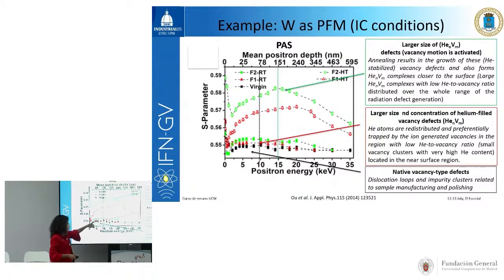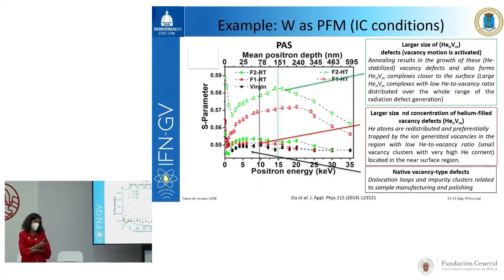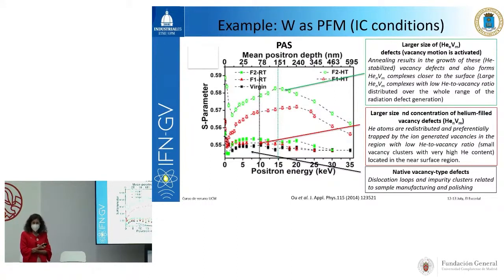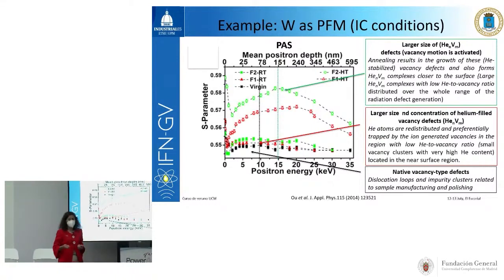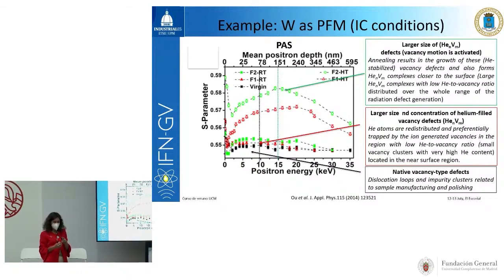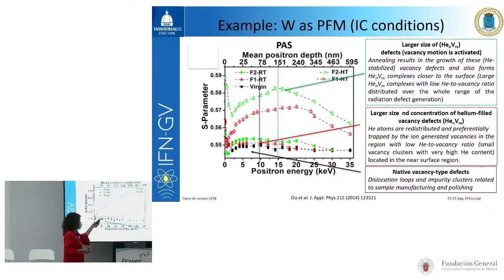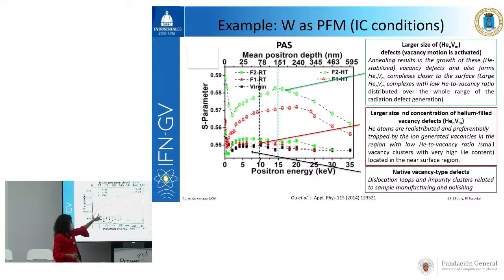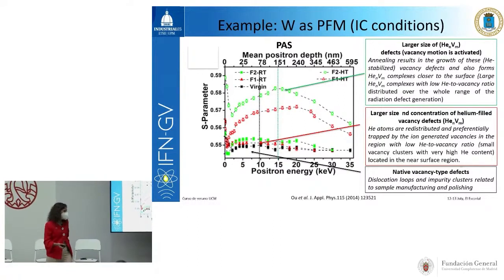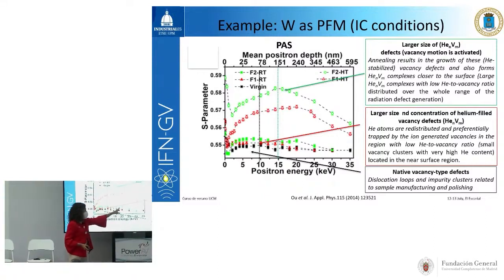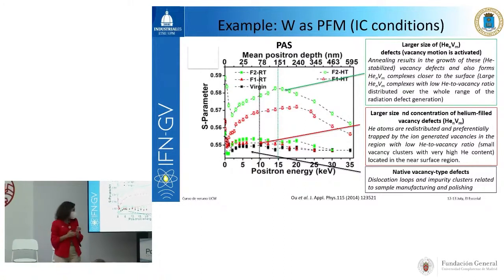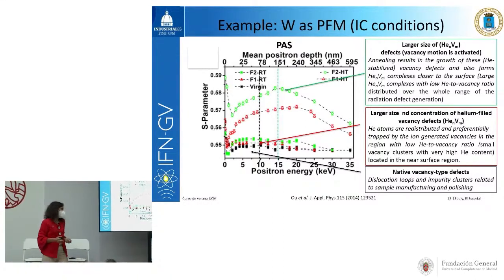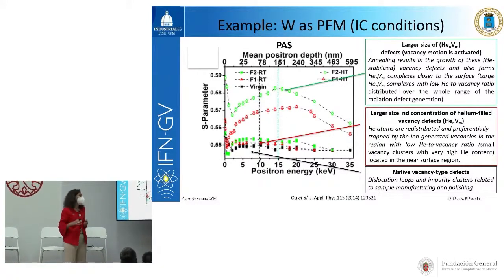This enhancement shows us that we have introduced some defects, vacancies, into the material, and this enhancement is lower than expected. This is basically because helium is introduced into the vacancies, and then the positron emission is different than if we have only vacancies without helium inside. Then we observed that when we anneal the sample after irradiation, the radiation response increased again. And it is not only that it increased, it is also that the peaks are shifted to much higher positron energy, which basically means that we are going to have helium vacancy clusters distributed all along the penetration range of the helium atoms.